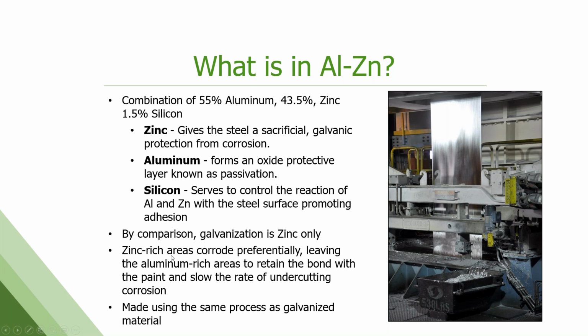So the rich zinc areas on this product are going to corrode preferentially, leaving the aluminum-rich areas to retain the bond both with paint, if it's painted, but also with the steel substrate underneath. So you get much less edge corrosion long-term with this product than you do with straight zinc.